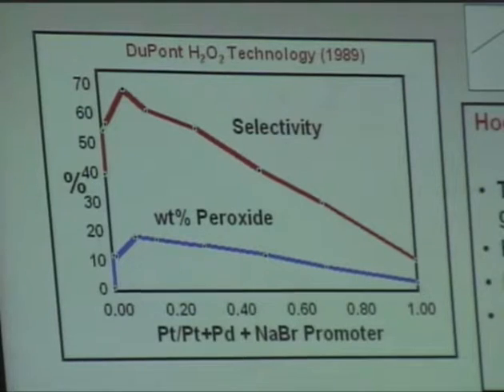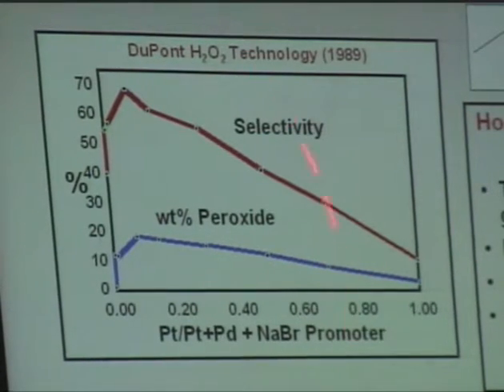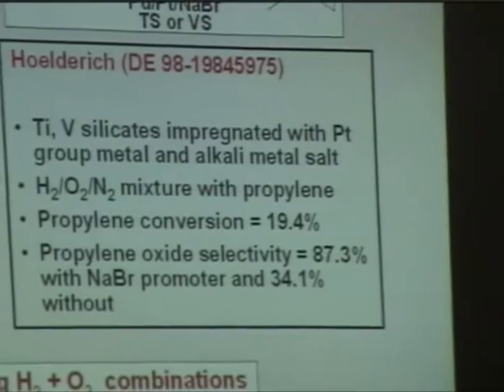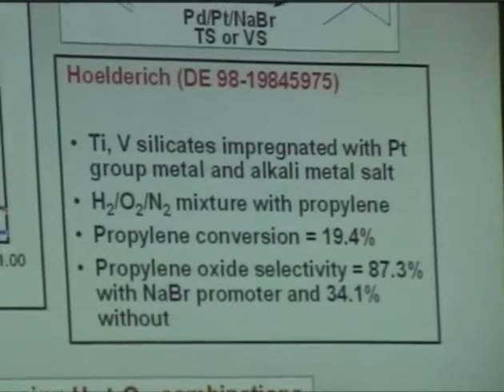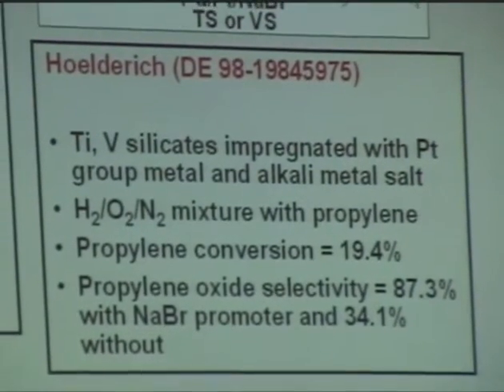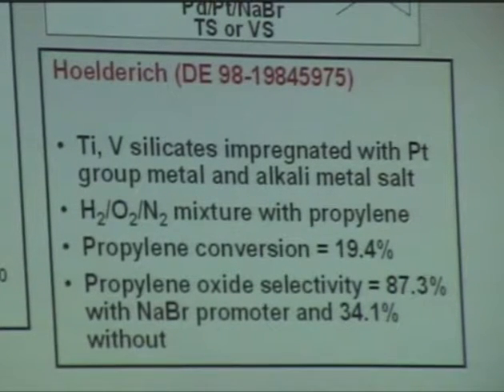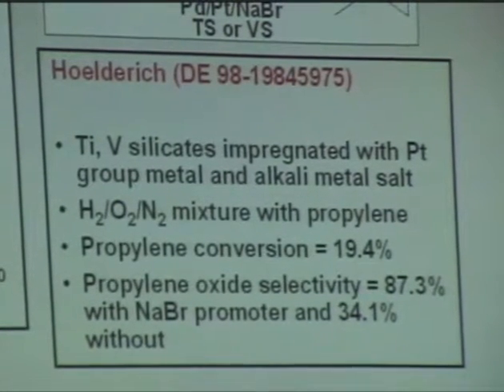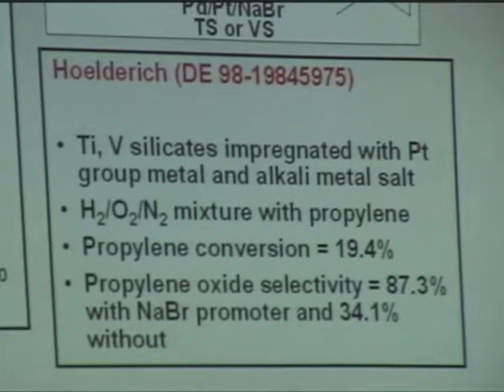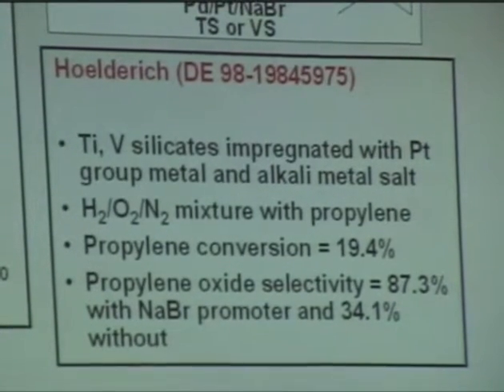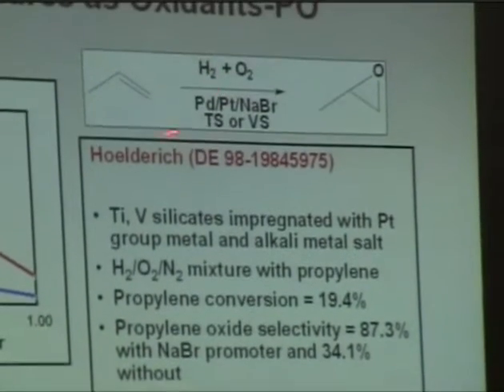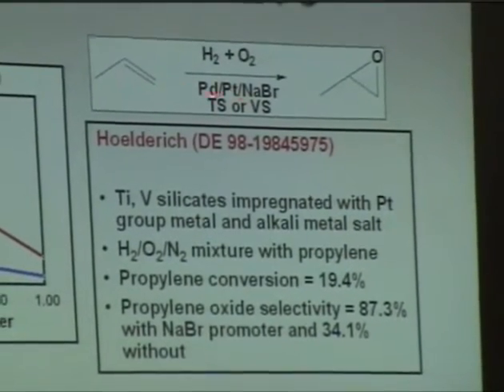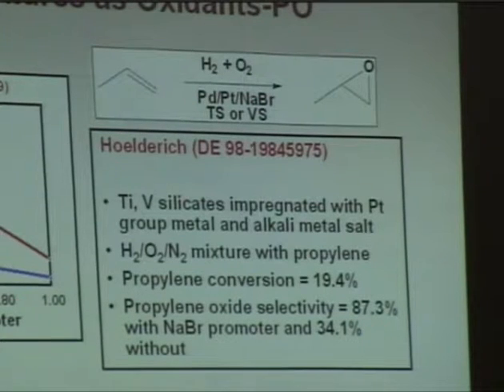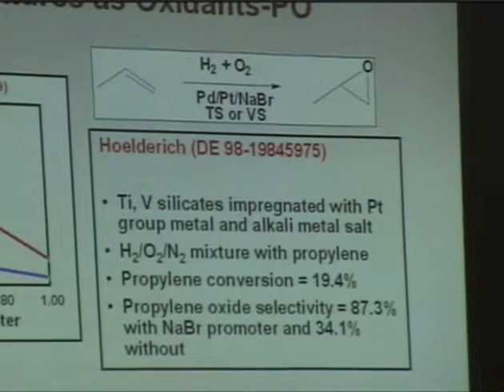Tremendous technology. Well, Wolfgang Hoelderich, I talked to Wolfgang many times about this catalyst system. He decided to go ahead and take the platinum palladium catalyst. Critical component is a sodium bromide promoter that's present in this system. So he took a titanium silicalite, vanadium silicalite type catalyst, the type of catalyst that does hydrogen peroxide epoxidations, deposited on that catalyst surface the appropriate palladium and platinum catalyst, and used sodium bromide promoter.